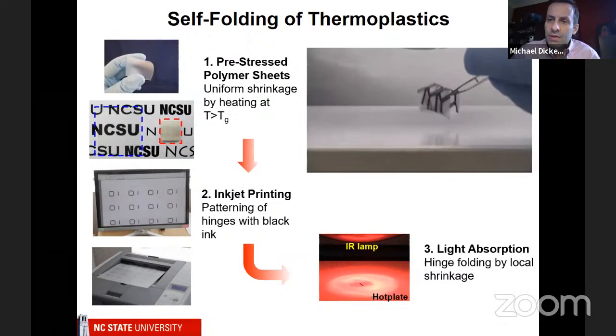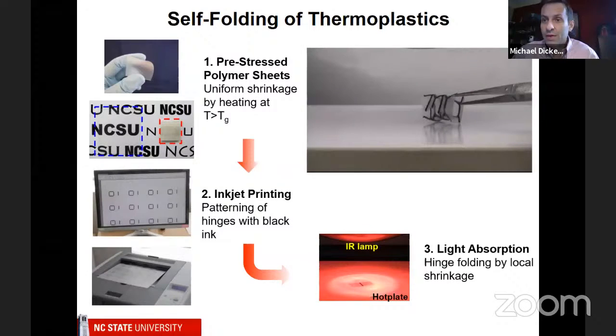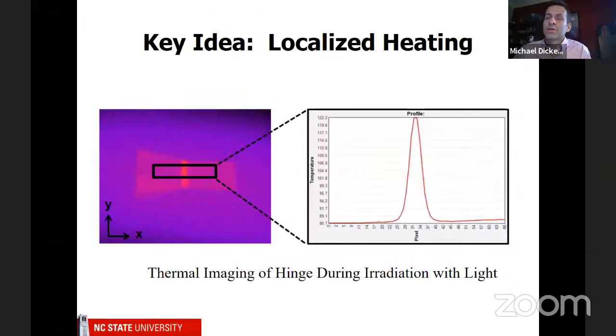All right, so the key idea, the thing that makes this work, again, is temperature. And we're just using light to deliver heat to the sample. So if you take a very simple sheet of this polymer and put black ink on it, which is shown here in red, and then shine light on it, now we're looking at this with an IR camera. You can see that when we shine the light, it gets hot. And if we plot the temperature on the surface as a function of, well, this says pixel, but this really should be distance, you can see that in this red region the temperature is hotter by quite a bit, about 30 or 40 degrees Celsius.